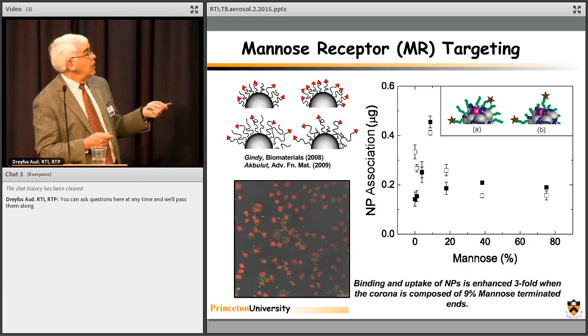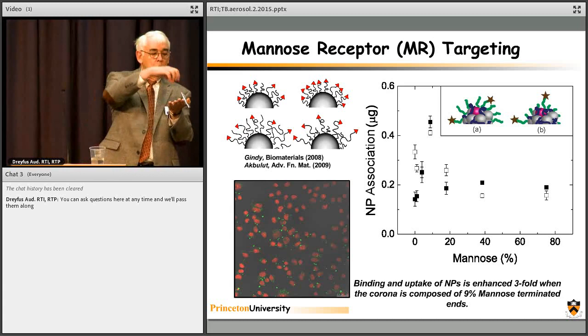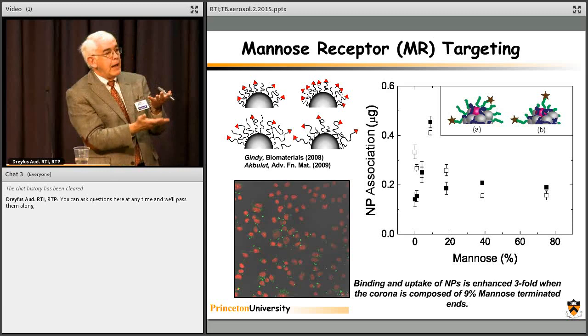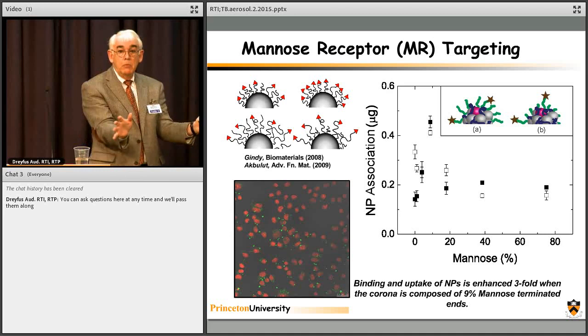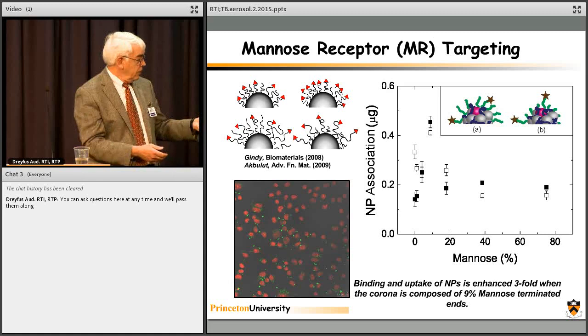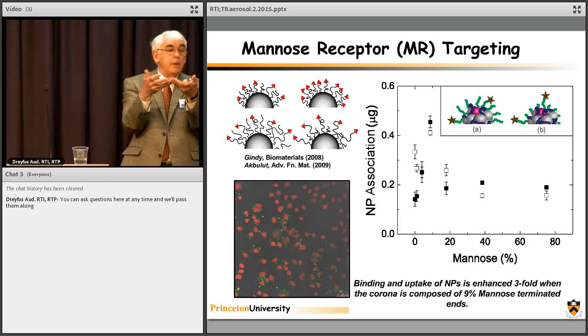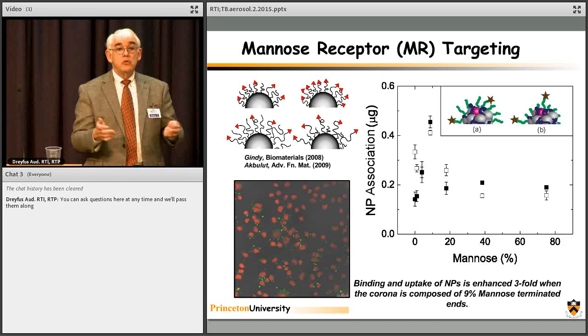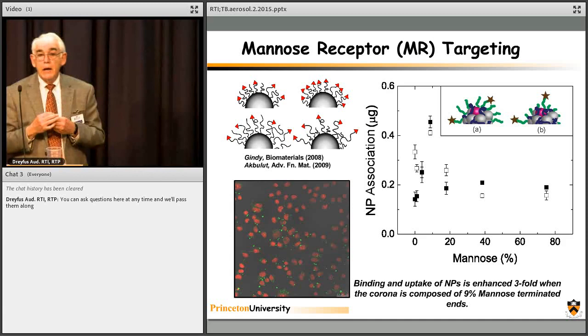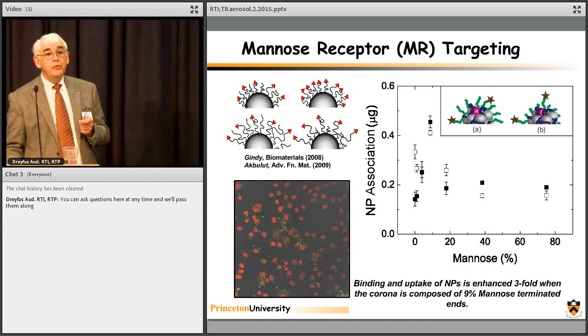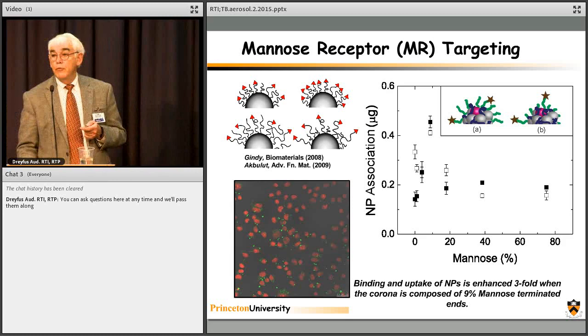If you look at these cells here, what's happened is that once the nanoparticle lights onto the mannose receptors on the macrophage, that starts a cascade inside the cell, which builds cytoskeleton, and it's supposed to invaginate and make an endosome. It apparently overstimulates that. So on a confocal, if you look at these particles out here, the place where the bright fluorescent spots are, the film has been raised up, it's a bowl. So it has rigidified that layer so much that it can't invaginate. They're still stuck on the surface, but once you decorate that surface, you basically blind the macrophage and you don't get any more uptake. So there's an optimum size, optimum density for uptake, which I think is a really important thing in this targeting field, to be able to understand what those are for different cell types you're targeting and different nanoparticles.